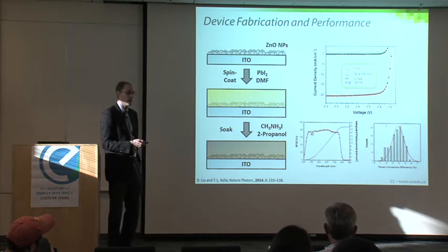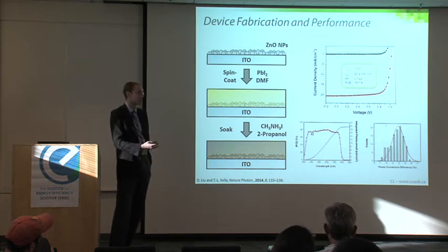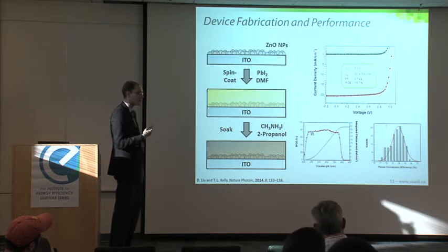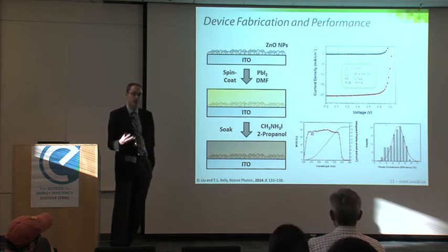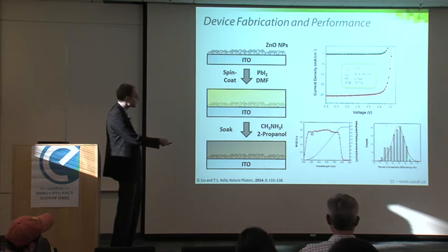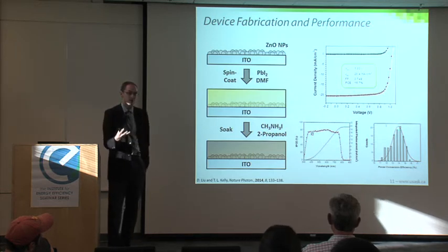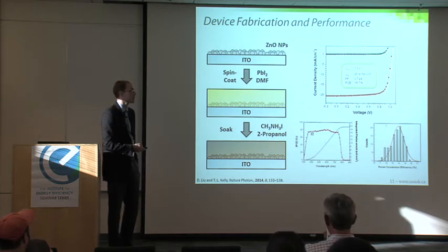They actually worked so well I didn't quite believe my postdoc at first and said, okay, go back and make more devices, more devices. So we had a nice distribution here of about 100 separate cells across multiple substrates. And of course, the kind of sneaky advantage to making 100 devices is you're statistically guaranteed a 3 sigma outlier, and that was our best device out here. And so even though our average is around 13 or 14%, of course, our best device is a little bit above that. So it was quite gratifying to see that we could actually make a high efficiency planar heterojunction.